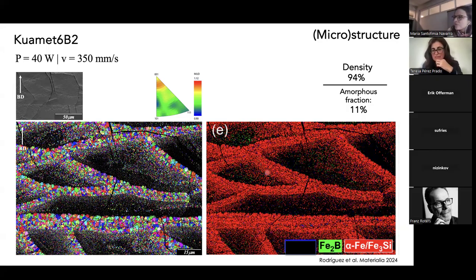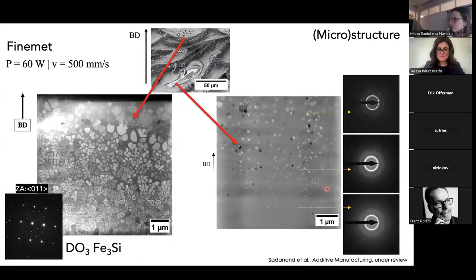And then on the right is a phase map of the same area. Again, most of it is red, which corresponds to this iron silicon phase, which EBSD cannot distinguish further. We can do that by TEM later. And we have a minor fraction in green in these regions of borides.